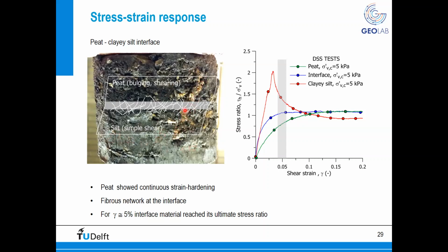Now, if you try to test these three materials, peat, clayey silt, and the interface, in a direct simple shear test, you can clearly see a completely different stress-strain response. The peat layer, which is the green stress-strain response, continuously shows strain hardening, so you don't reach failure, even at a shear strain of about 15%. But if you look at the interface, which is the blue line, already at 5% of shear strain this material already mobilized the maximum stress ratio. And 5% was actually the shear strain at failure that we estimated from the field test.